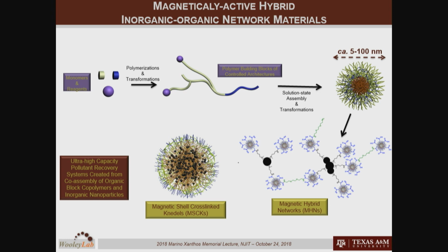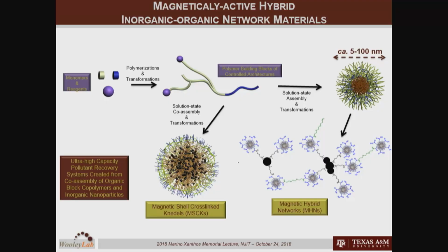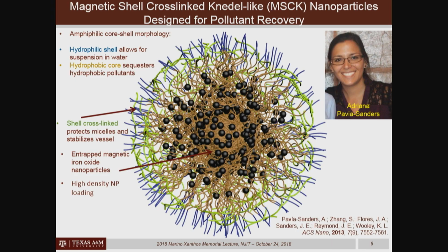If alternatively we take the block co-polymer that is designed for supramolecular assembly and don't assemble it and stabilize it and then couple it to the inorganic particles, instead, if we co-assemble it together with the inorganic particles, then during the assembly process, those inorganic particles can be trapped inside, and then stabilization reactions can be performed to generate what we're calling MSCKs. And so we're going to start with these materials as the first that we elaborate upon.